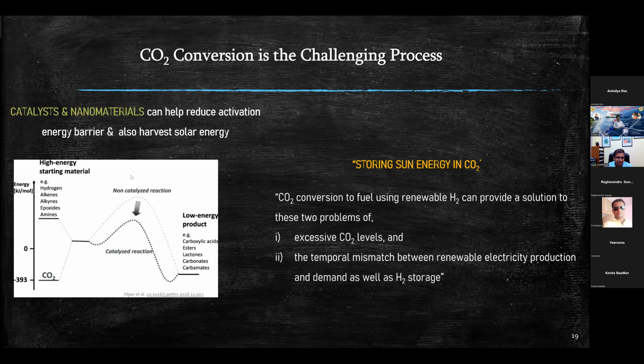So what we are trying to do is develop a catalytic system, nanomaterials, which will chemisorb the CO2 onto the surface. Once CO2 chemisorbs onto the surface and interacts with the surface, the CO2 is no more linear, but it bends a little bit. The bond angle changes, the bond length changes based on the interaction strength. And that makes that CO2 reactive. Now the activation energy barrier goes down. Whatever remaining activation energy barrier is still there, that energy should come from the solar energy. So I'm using the solar energy and the nanomaterial absorbing the CO2, and I'm going to split the water into hydrogen and oxygen, and that hydrogen will be added into the CO2. So I'm storing the solar energy into the CO2, I'm storing the hydrogen into the CO2.